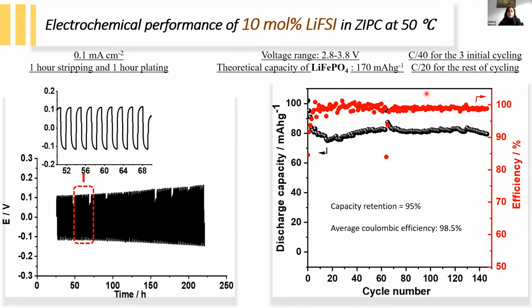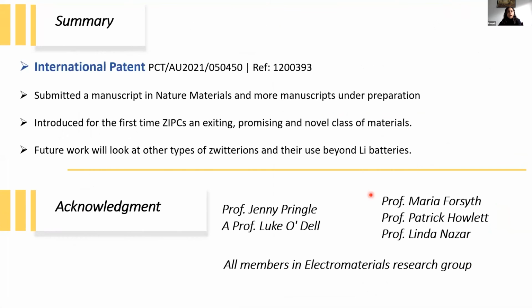And initially at the low C rate, we saw that the cycling performance is very stable. We are still working on these materials to improve the cycling performance of this plastic crystal, again in collaboration with Battery Hub. And also interestingly, it is very important that Coulombic efficiency is also very high in these materials. So all these results show that we can use Zwitterionic plastic crystals in energy storage devices.